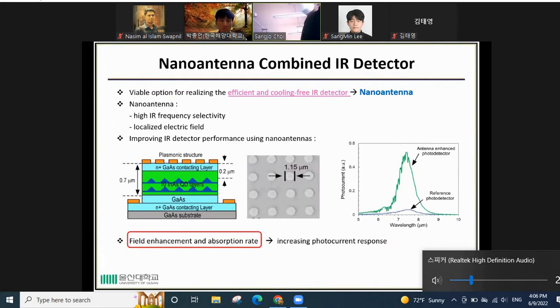One suitable option for realizing an efficient and cooling-free infrared detector is the nano antenna, because the nano antenna has characteristics such as higher frequency selectivity and also localized electric fields. So this is an example of a nano antenna being used for improving infrared detector performance. This is an infrared photodetector combined with a plasmonic structure. From this, you can see that the photocurrent increases after the addition of the nano antenna. The increase of the photocurrent is because of the electric field enhancement and also the absorption rate from the nano antenna.